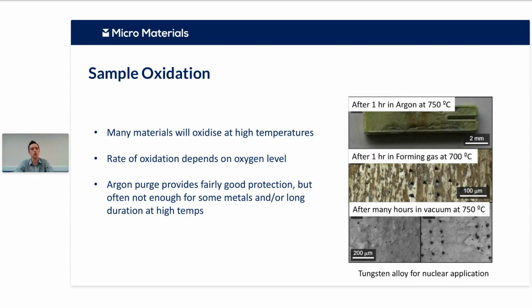In terms of sample oxidation, of course, many materials, metals and alloys will oxidize at high temperature, and this oxide layer significantly interferes with the nanomechanical characterization that we are trying to do on the sample surface. So we need a way to overcome this limitation. We can perform the test in a protective gas purge environment, for example, argon purge, which is what we use for our non-vacuum system. We have a purge capability there. This is sufficient to slow down the rate of oxidation, but it's often not enough for some metals that are readily oxidized,